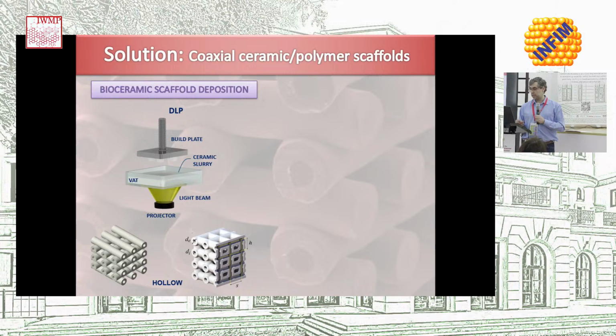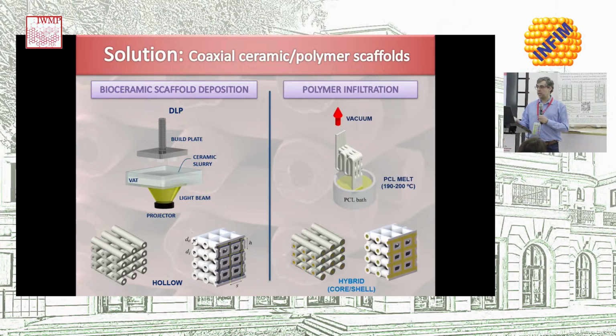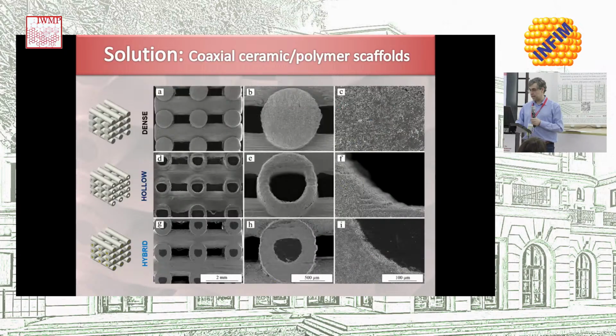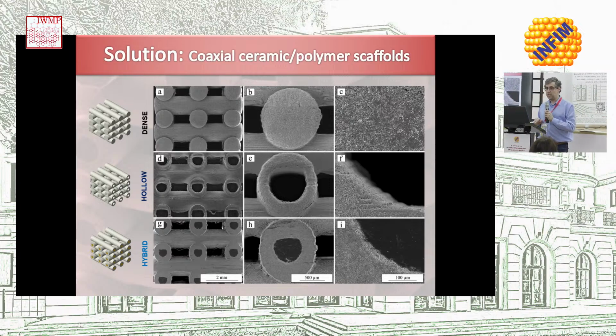Once we have this printed, what we do to incorporate the polymer is simply infiltrate the internal channels by using a suction method. We put some inlet and outlet in our scaffold, and then by applying a vacuum, we suck a polymer melt inside those channels, and we fill these internal channels with the polymer. And we did that, and in fact, as you can see on this slide, we were able to produce those structures. You have the dense struts, hollow struts, and then at the bottom you have the hybrid structure, in which we have the polymer, PCL in our case, filling completely the internal channels of these scaffolds.